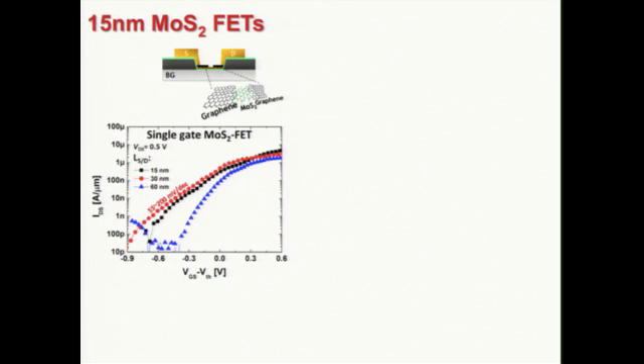This is the device. Here we see 3 transistors with 60, 30, and 15 nanometer channel lengths. I should mention that the minimum channel length that worked for us, in terms of the patterning, was 15 nanometer. Although we can see the 10 nanometer, it's not fully developed, so there is still some graphene residual there.